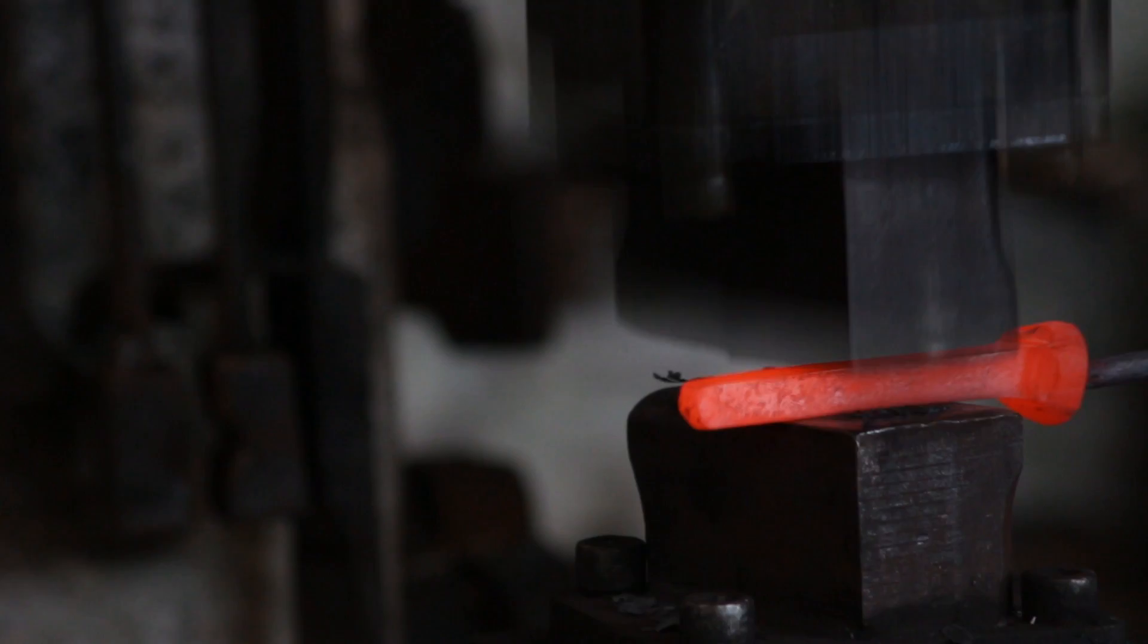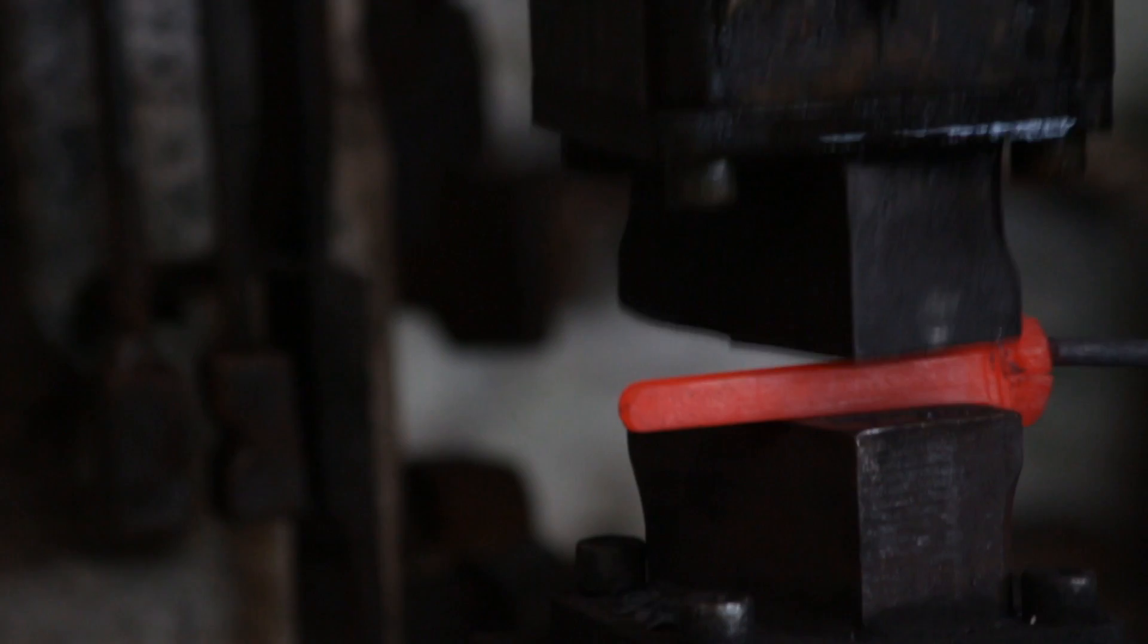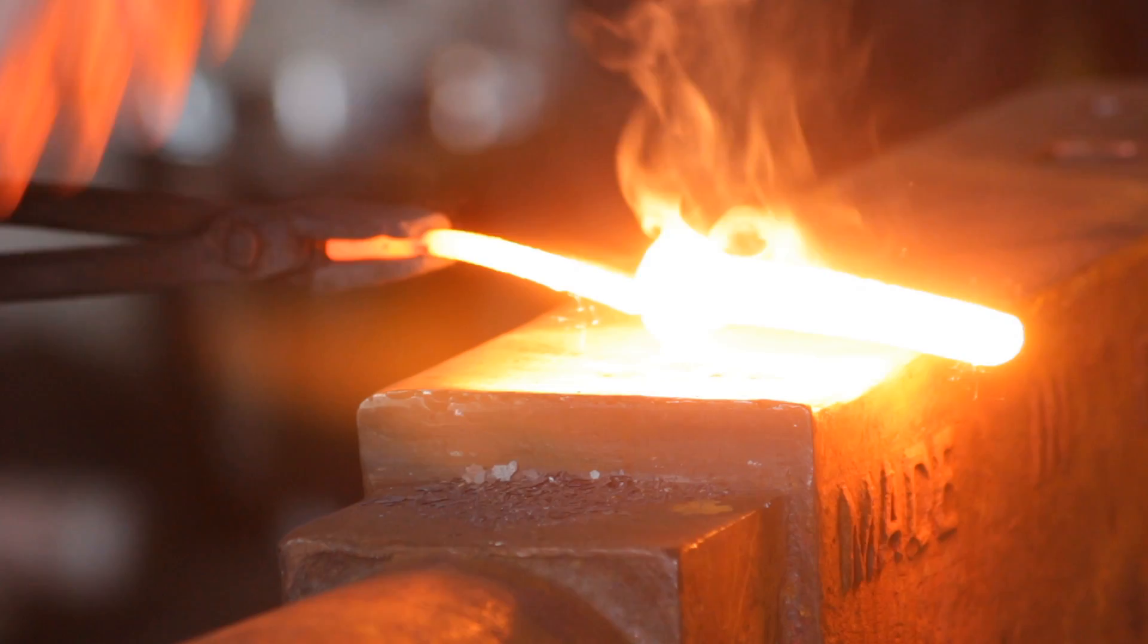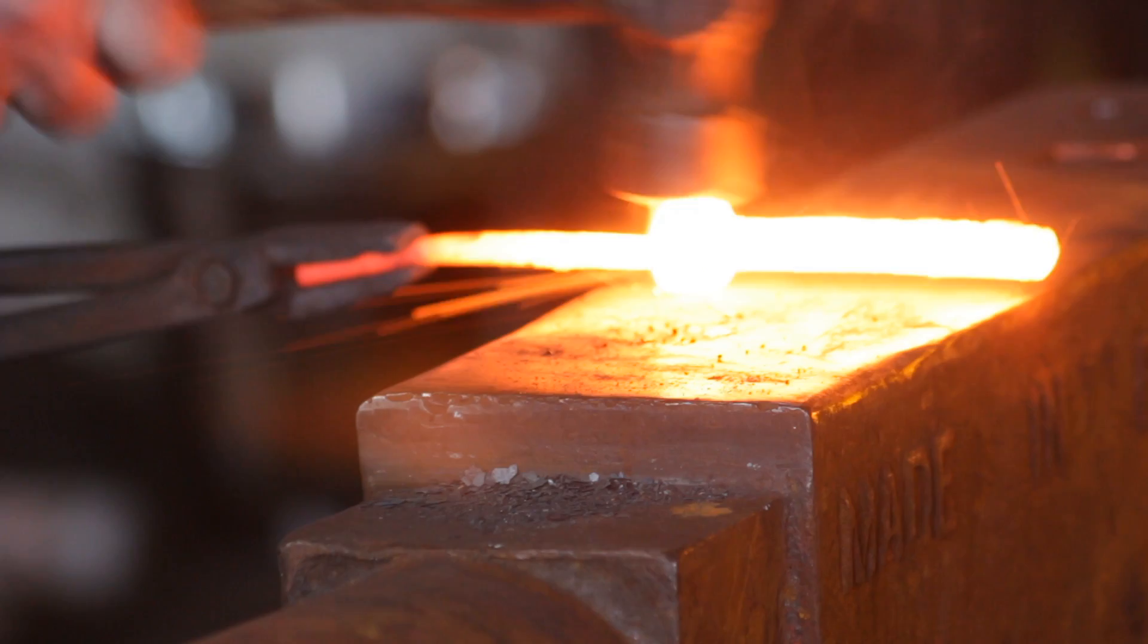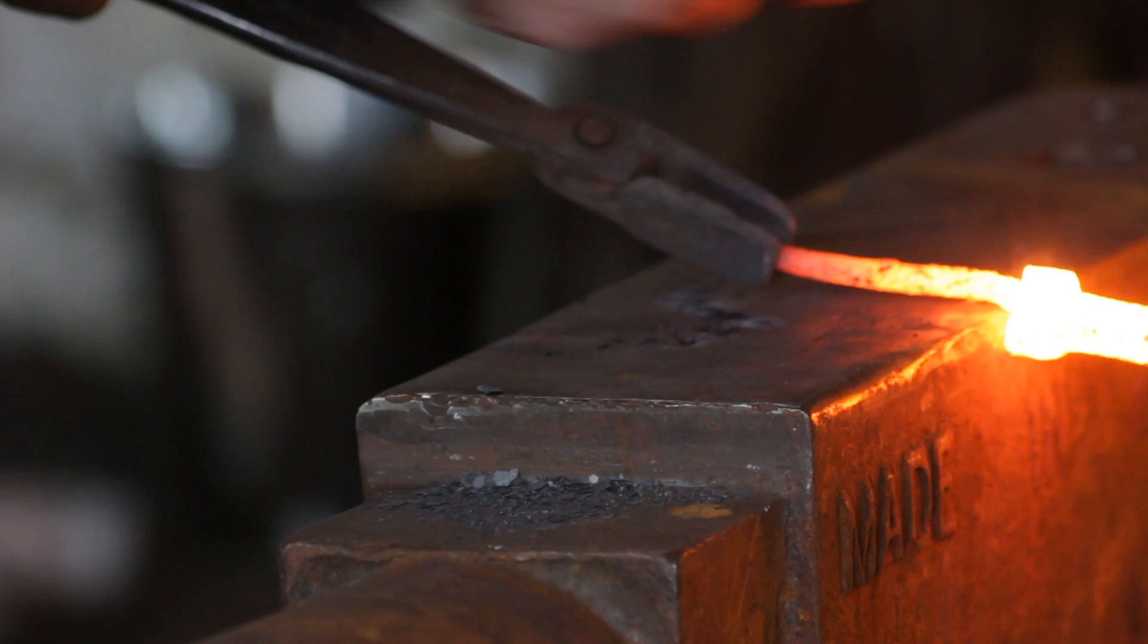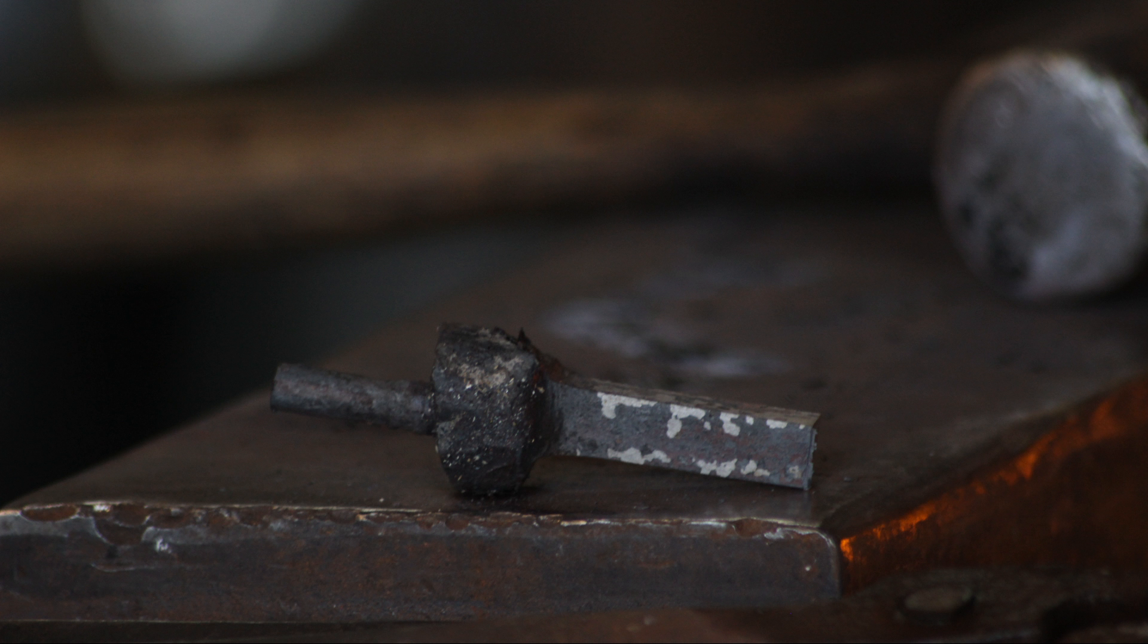So I drew this out to approximately 10mm square which gives me this. Now because of the splitting that was occurring I then took a welding heat. And I actually used a little bit of flux for this which I don't normally do with wrought iron. And just welded up that delamination back together. And the reason I used flux was because I was worried about that tenon at the bottom so I didn't want to overheat it.